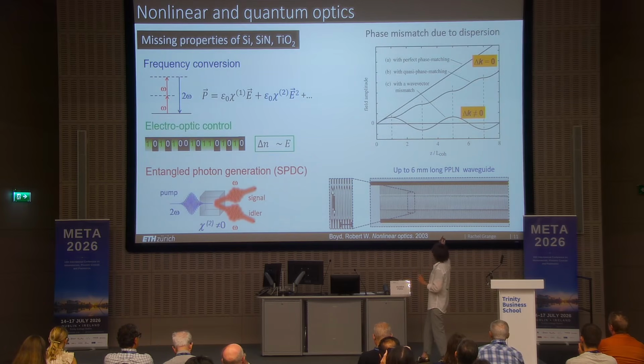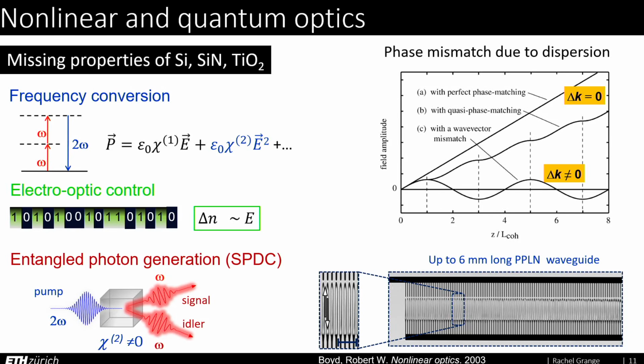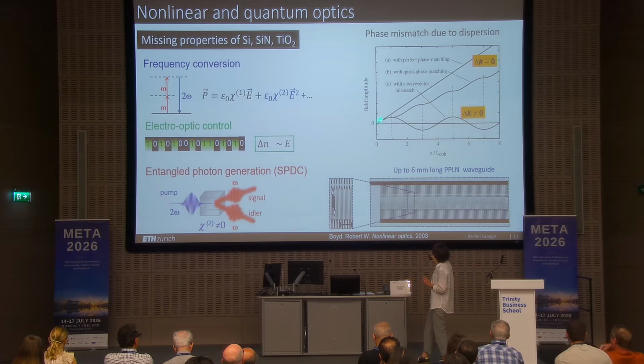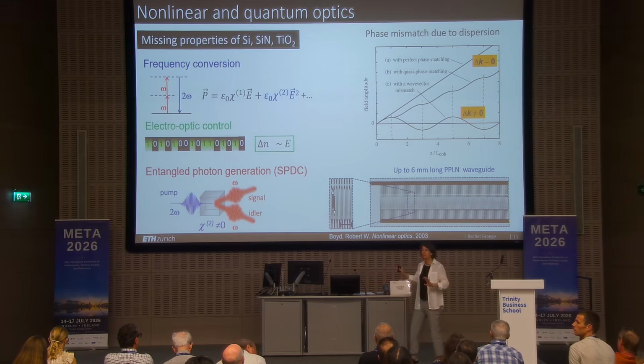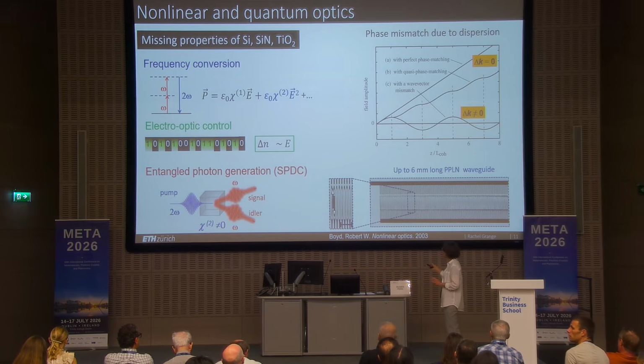So you have phase mismatch due to the dispersion, but mostly in flat photonics, we are below the coherence length of our material. Typically for lithium niobate or barium titanate it is 2 micron. So for everything below 2 micron, you don't need to do periodic poling, you don't need to invert your crystal here, as you can see is possible on chip, and you stay in this region where there is no need of this kind of